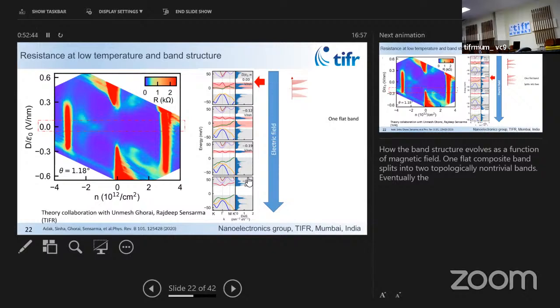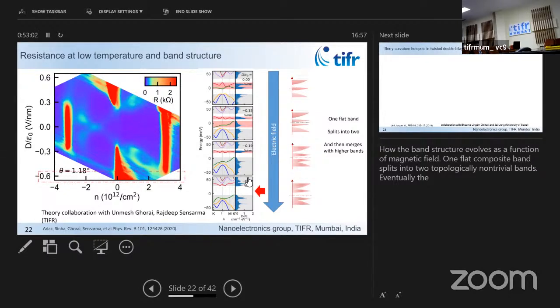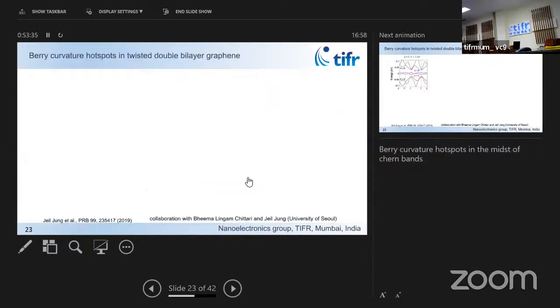Now, if you apply an electric field, which is basically moving up and down, it will become clear. You actually slowly, these 2 bands which are overlapping, you open up a band gap in between, and then further band gap. Eventually, these 2 bands will move, and it will become somewhat merged. The flat bands will merge with the remote bands, and there will be a large gap. And the electrical response is these gaps that you see here at this energy. These are the gaps due to the moiré periodicity, which is the additional periodicity that we have. And this direction changes the electric field. Here it starts with a metal somewhere here, and then you open up a gap. It becomes a semiconductor, which is showing an insulating response.